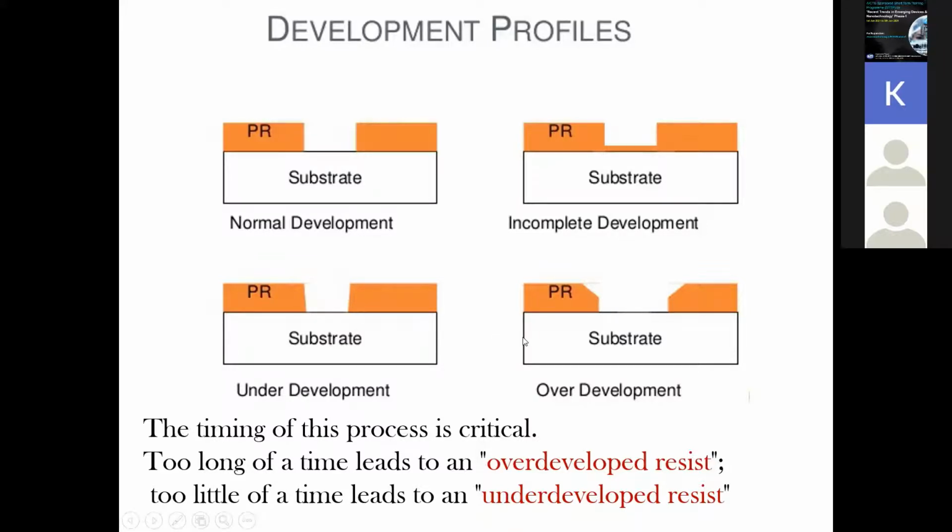Whereas if you do it more, at the boundary region there will be etching out of the photoresist also where it should not be. So this is called overdeveloping, and you should avoid this one. Otherwise, if you overdevelop, your size will increase. Let's say you try to make a 200 nanometer by 200 nanometer pad. Now, if you do an overdevelopment, this 200 nanometer may go up to 250 nanometer by 250 nanometer. So you can understand how much error will be incorporated.